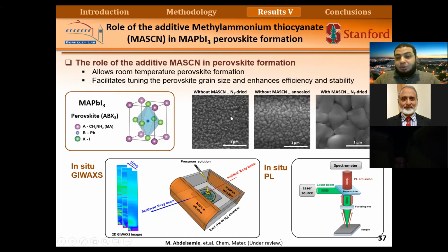It's a salt material that we add into the precursor solution. And we have found that if we don't use this, we end up with a film that has small grains of crystals surrounded by unconverted material. So the dark colors here are just material that is not converted. So we need thermal annealing in order to form the perovskite phase. But if we use the additives, we can form very large, micron-sized crystals of perovskite at room temperature without the need for thermal annealing. But here also we need to dry the film. We can use nitrogen drying to dry the film, or we can use low vacuum to dry the film.